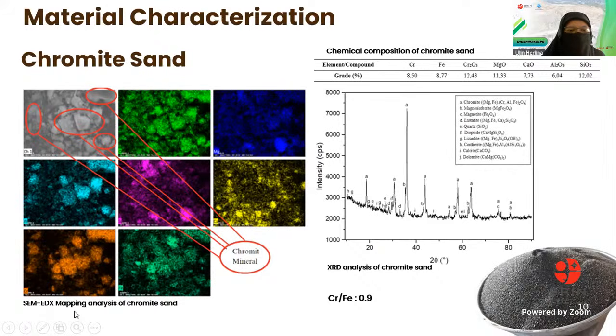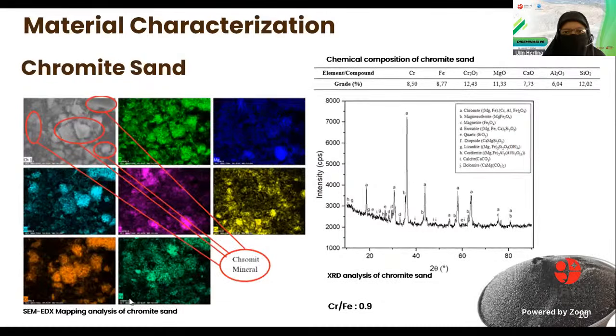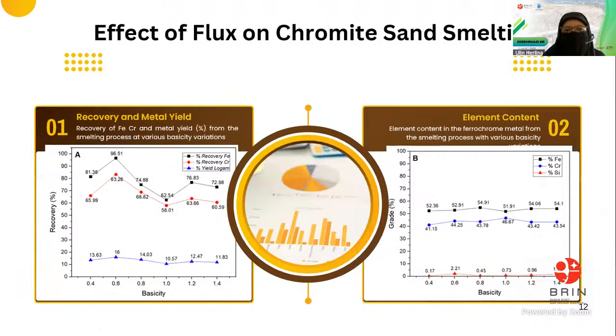In SEM EDX mapping, we can see that there are elements that are separate, or not directly bonded to the chromite compound, and also it has impurities that are directly bonded to the chromite compound. So this chromite sand has to pass beneficiation before we process it to ferrochrome.